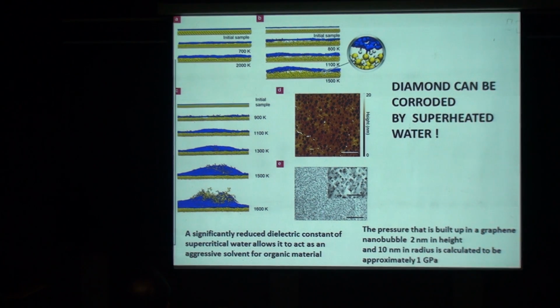adverse, extreme conditions. You have to use catalysts, you have to use very strong conditions. But water corroding diamond, I think this is the first time people report such a thing. It is quite incredible. Now the water that's trapped within the bubbles becomes supercritical and starts to corrode the diamond. So we can form these pits. Diamond becomes corroded. This gives us a clue. If you perform hydrothermal chemistry using water at high pressure and high temperature, maybe you can corrode diamond.